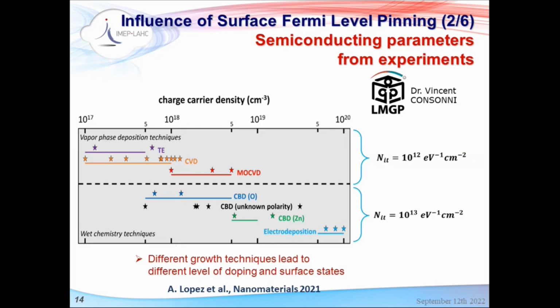But now, in reality, the surface traps depend on many things, in particular on how you fabricate the nanowires. And there are many techniques to fabricate them. There are vapor phase deposition techniques, wet chemistry techniques. And in this graph, you can see that all of these techniques produce nanowires with different doping levels, and also different density of traps.